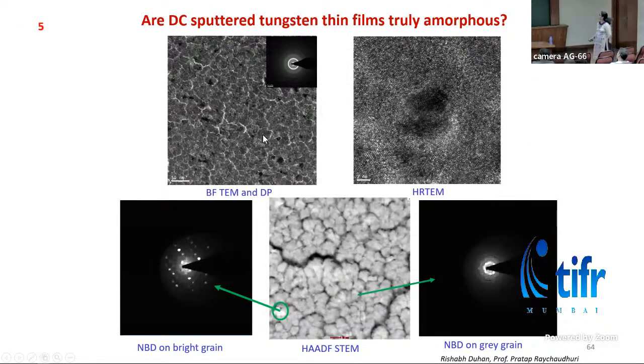Here is an example of DC sputtered tungsten thin films. These films are very thin, about 20 to 30 nanometers in size, so it is difficult to get crystallography information from these films. Because if it has small inclusions of 5 nanometers or 2 nanometer crystallites, then definitely X-ray is not going to pick it up. This is a high resolution TEM image showing the dark contrast in the center, which is a crystal about 5 nanometers thick.